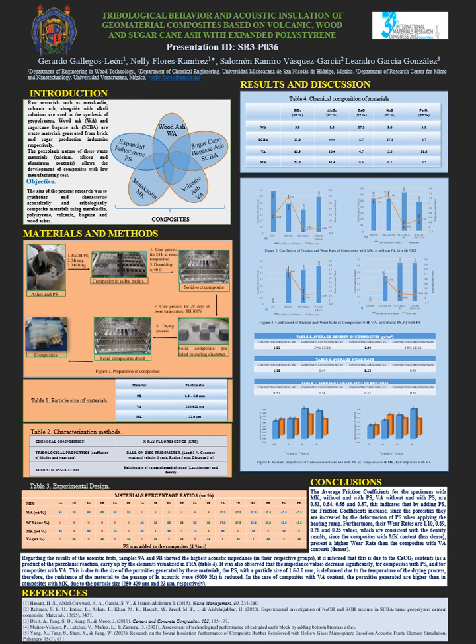This is due to the size of the porosities generated by these materials. The polystyrene, with a particle size of 1.5 to 2.0 millimeters, is deformed due to the temperature of the drying process. Therefore, the resistance of the material to the passage of acoustic wave